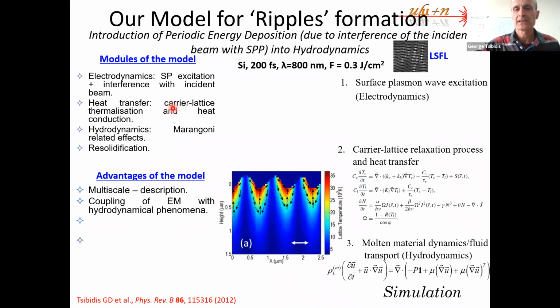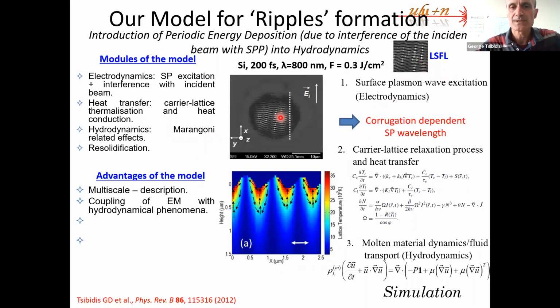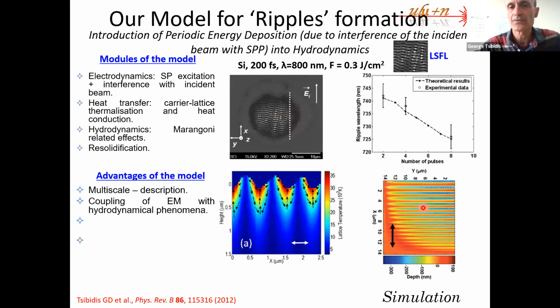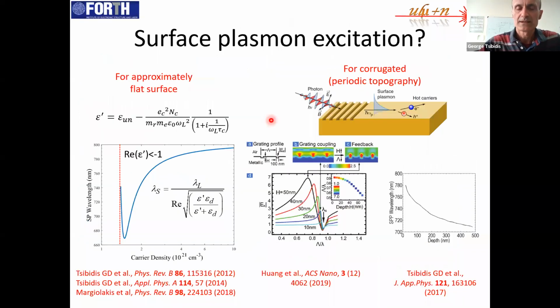So what happens is that this periodic modulation is going to be transferred into the electron temperature and, through electron-phonon coupling, to the lattice temperature. When the material melts, because we assume that conditions are sufficient to melt the material, then all the hydrodynamical parameters will have a periodic profile. So you see what is the fingerprint on the fluid, which of course remains upon solidification. In the end, we get this surface profile, this pattern, which exactly is the pattern of the LSFL structures. And you see here the result of the experiment and the similarity of the simulated experiment with the real experiments.